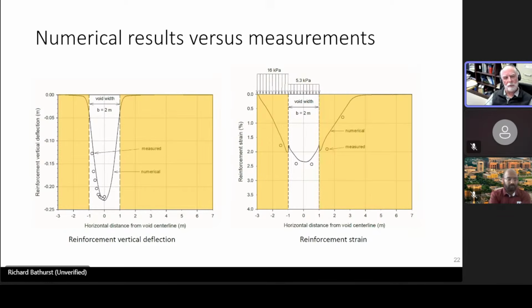And then we did the same thing with the strains. And here you can see again the symbols represent the strains in the reinforcement as they span this void, and the solid lines are the numerical approximations or predictions. And you can see that again, we judge the agreement to be quite good.